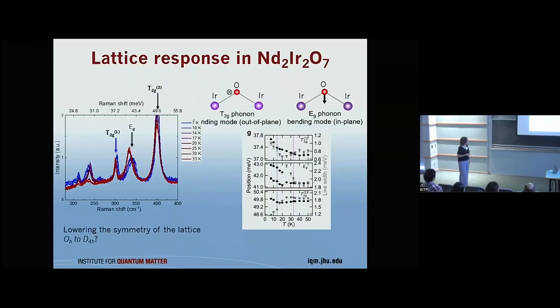One minute. Raman scattering measures phonons. That means that we see the response of the lattice, and actually in most of the magnets we're looking at, we always see that something is happening with the lattice. A lot of times we see smaller changes in the frequencies of even gamma point phonons than XRD could observe, and we can discuss why. So we actually see a pretty, unexpectedly, strong response of the lattice. There was supposed to be no structural transitions. All these changes in the lattice, in these three oxygen phonons, are continuous, so there is no sharp phase transition. And we are still thinking about it.